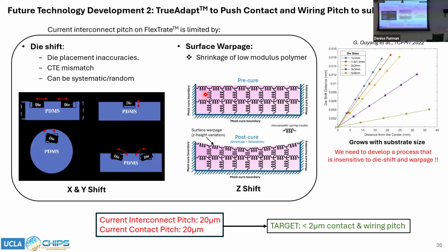And sometimes during the curing process of the PDMS itself, because of the shrinkage of the PDMS, there could be some kind of XY shift of the dies or rotation or tilt of the dies. Similarly, there's also surface warpage because most of these polymers, before curing, you can model as a bunch of springs. But after curing, because curing involves a shrinkage, you can imagine all these springs now want to come close together, and therefore it creates kind of a meniscus on the surface, and therefore you have a bow. And both of these basically lead to a situation where you have both an XY shift as well as a Z shift in the dies.